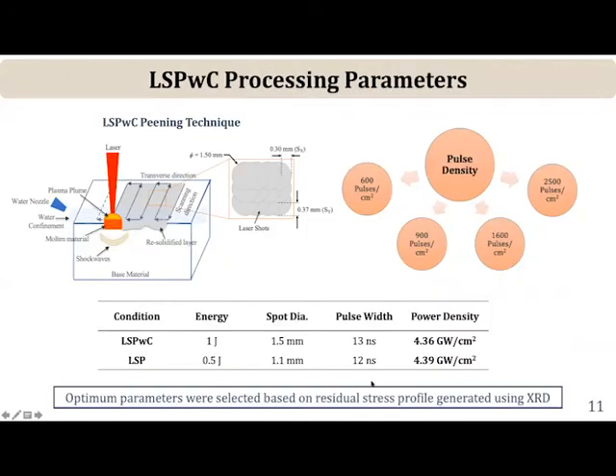Okay, so what Anurag did, of course, was with regard to these LSPing without the coating, which was coined as LSPwC, following the original work of Yuji Sano, who's going to be speaking later, shows the methodology he used for doing this peening without the coating. But prior to selecting what kind of conditions to use for more detailed study, Anurag initially looked at the impact of pulse density, basically changing the degree of overlap and the number of hits per unit area to set up some initial conditions for further study. Okay, so this shows the conditions.